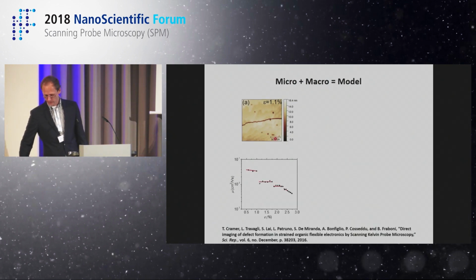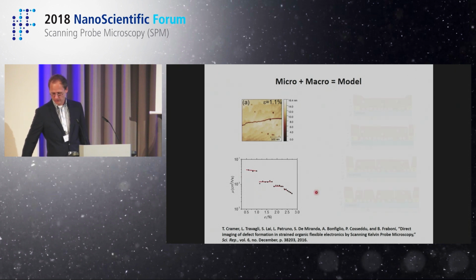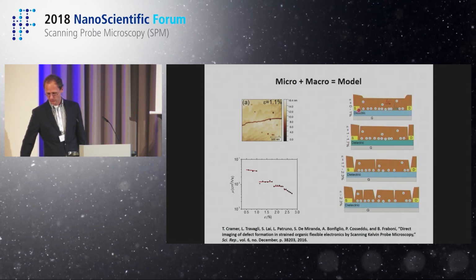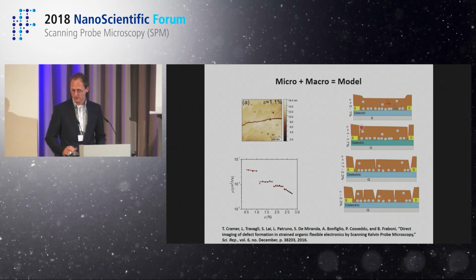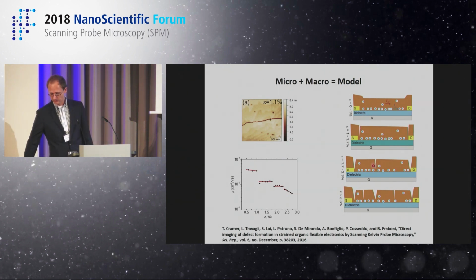So combining this information from the microscale and the macroscopic behavior, now I understand that initially, of course, I have a nice channel. Once there is the appearance of cracks, I have barriers in transport, but it remains stable for some time because these cracks can absorb some strain, and then I continue by breaking it. I have the appearance of additional cracks, and the mobility drops down until it's completely destroyed.